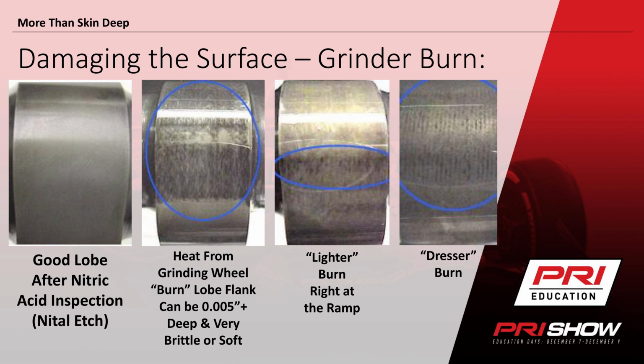Now, if you're just a dude racing and you think you might have a burnt camshaft, you might not have nitric acid. You can buy it from Pace Technologies, by the way, pre-mixed and everything. I think they're in Arizona. But you can go over to a glass bead cabinet, and if you shot it with glass bead, you would see that the part that looks black there would be soft and would look duller. The reason it looks duller is because the glass bead goes deeper into the surface where it's softer, and shows you that soft area.